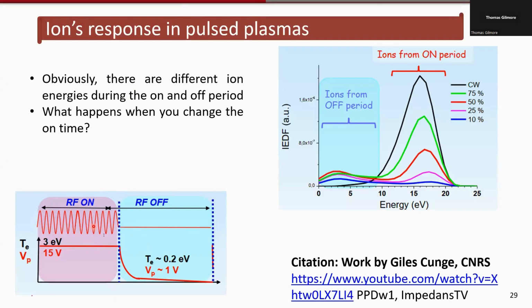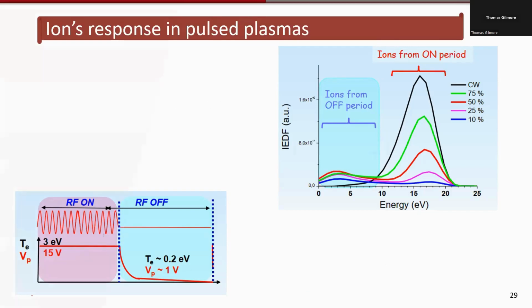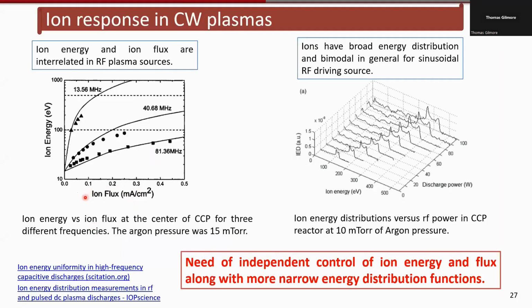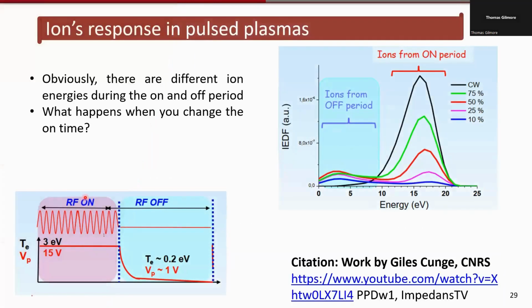And this gives you some advantages. It allows you to apply much more power in order to achieve higher energies, but without massively increasing the amount of energy you deposit in the tool. If you go back one more time to this diagram, if you want to increase energy, it goes pretty much with the square root of the power. So in order to double the energy, you have to go four times the power, and eventually it gets to the point where it's just an unusable amount of power being delivered to the tool to get the ion energy you want. But by pulsing, you can apply the large powers and decrease the average power that's being applied to the tool. So it's more manageable.